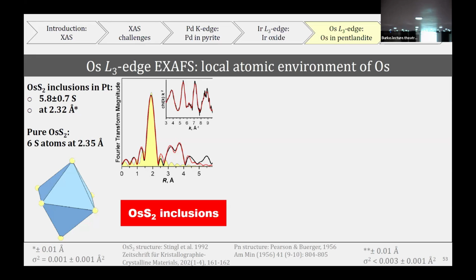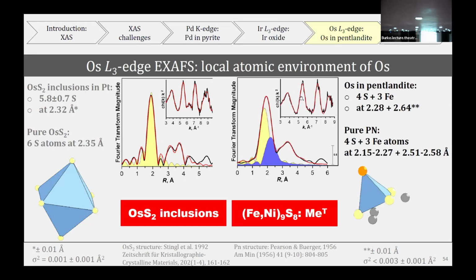sulphide in these inclusions. And also we proved that, unfortunately here we are working with an extremely short XAS spectrum, that even in this case, we can see clearly all the information. And for osmium in pentlandite, even though we suspected the octahedral state, it's certainly not the octahedral state. We tried all the hypotheses I showed you at the first slide, and they didn't work apart from one, and it's a tetrahedral position. So incorporation of osmium in pentlandite requires this.